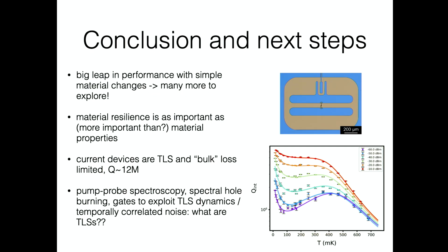Okay, so let me just give you one quick takeaway before I get into the unpublished stuff. Maybe the biggest takeaway is that we saw a really big leap in performance with just trying one more superconductor. The whole community had charitably looked at like five superconducting films, and then we're stuck at the state of the art because they were really trying to hit the problem with the only hammer that they knew, which was microwave design. And I think just by trying something, we were able to get this big delta in the state of the art. So it's probably time for people to do a much broader search. I can write down like 20 or 30 superconducting metal films, varying composition, that are easy to deposit and fabricate. So it is worth the big search now that we have a good playbook for understanding the materials losses.